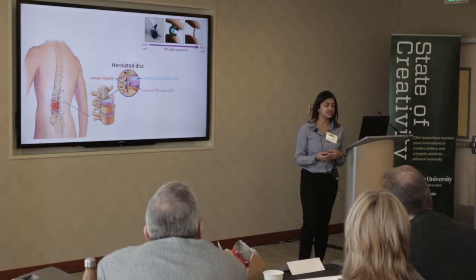My research is focused on the herniated disc problem. As the chemical engineer on this highly biomedical project, I've developed a water-based polymer material to address this problem. This material can match the stiffness of both the inner and outer parts of the spinal disc through specifically tuned stiffening. The exciting part is that we do this with the application of ultraviolet light — the more light the material sees, the stiffer it becomes.